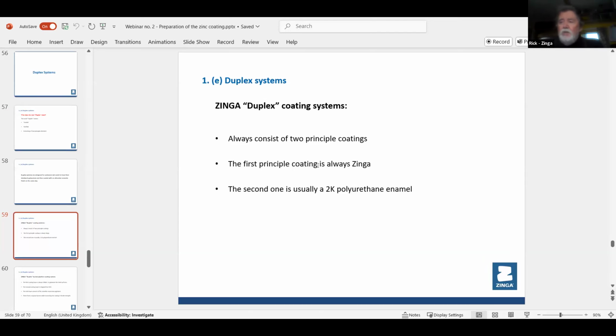So what happens with the duplex when you're spraying paint over Zinga? Your first coat is very light. You go off, have a cup of tea, come back after 50 minutes and look. If you look down at it, it should be completely matte. That means that the zinc has sucked all the coating into its porosities. That's why you do this, because all zincs are porous. All zincs have little porosities. So you put a very light coat, it gets sucked in, it's completely matte. That indicates that it's dry, now ready for the second coat.